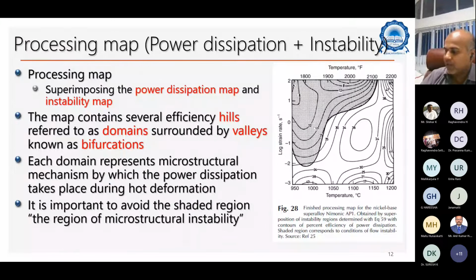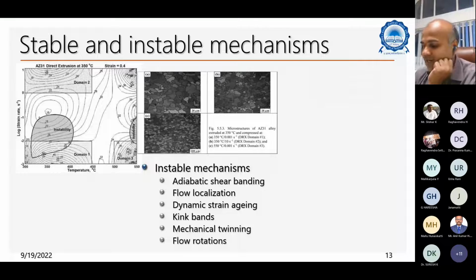Let me go back in detail. When you do a process in this region, how does the microstructure look? And when you do the operation in this region, how does the microstructure look? The difference in microstructure between this and this region. Here, stable and unstable mechanisms I'm talking about. This is one such processing map developed for AZ31 alloy. Okay, AZ31 is a magnesium, aluminum, zinc alloy: magnesium with 3% aluminum and 1% zinc. When you do this processing operation, this is the instability zone.